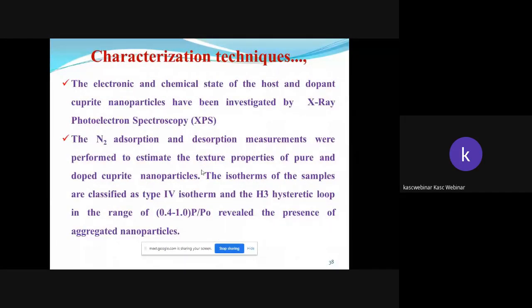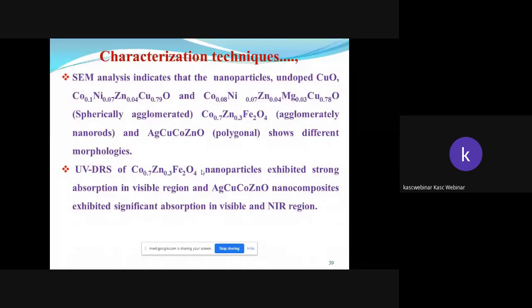The average crystallite size is calculated by the Debye-Scherrer formula. The electronic and chemical state of the host and dopant cuprite nanoparticles have been investigated by X-ray photoelectron spectroscopy. The nitrogen adsorption and desorption measurements were performed to estimate the textural properties of pure and doped nanoparticles. SEM analysis indicates different morphologies.